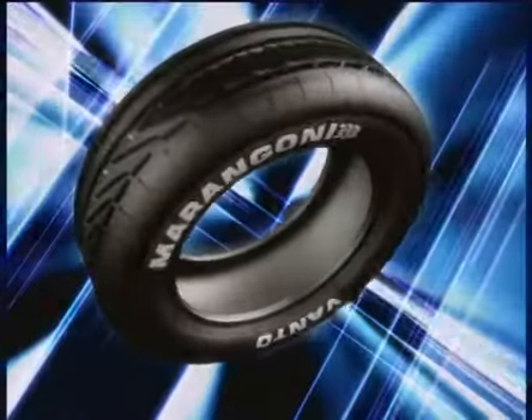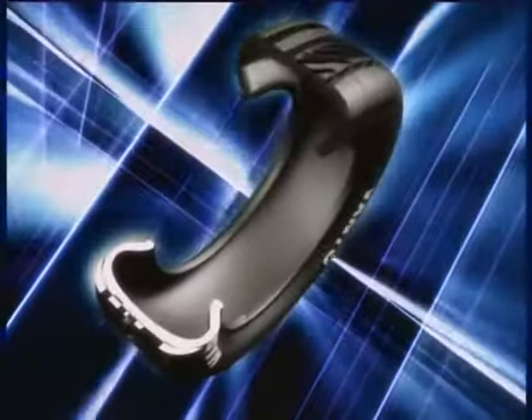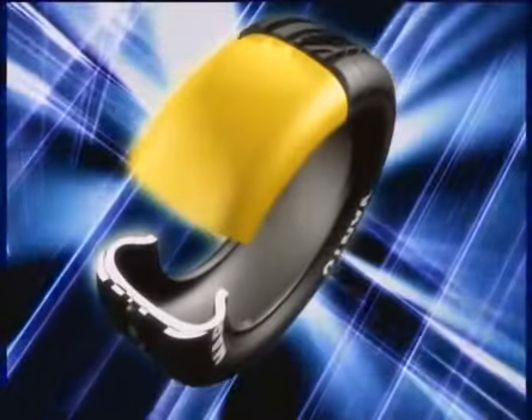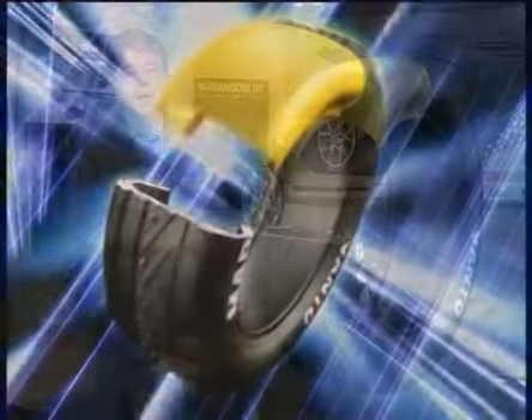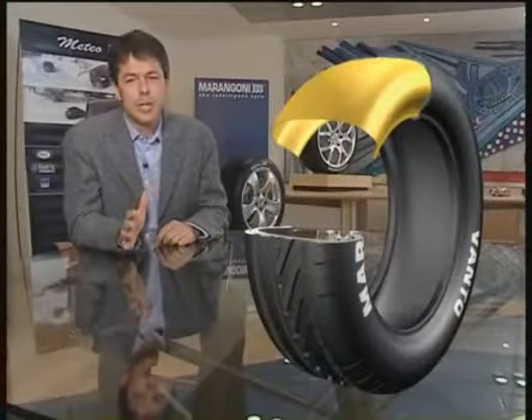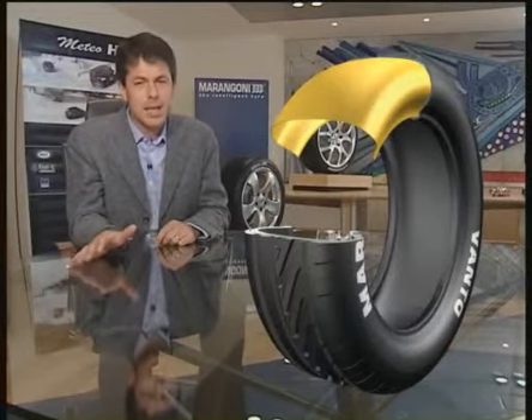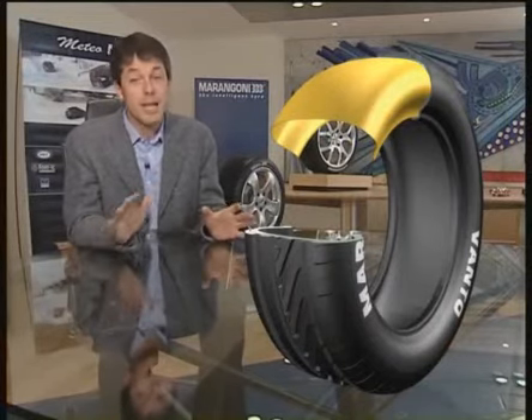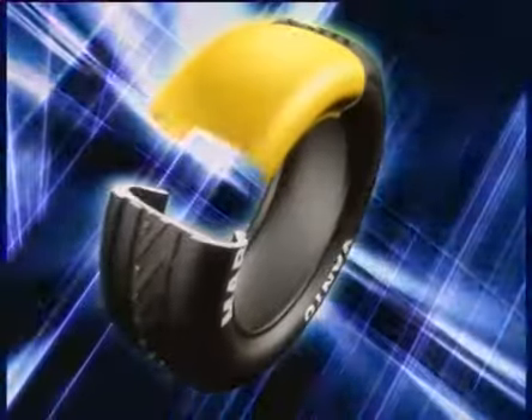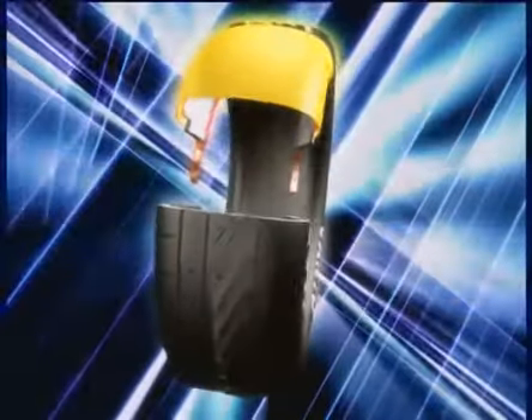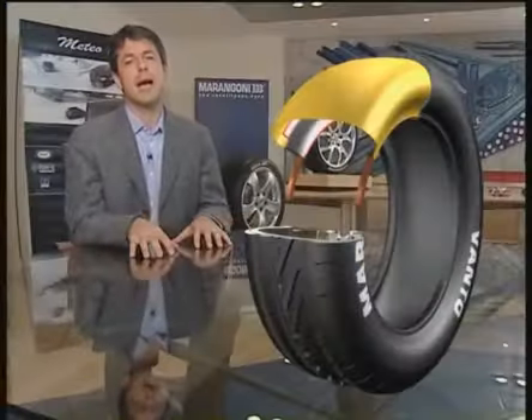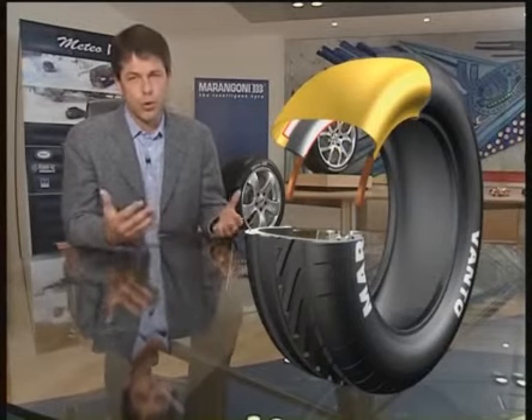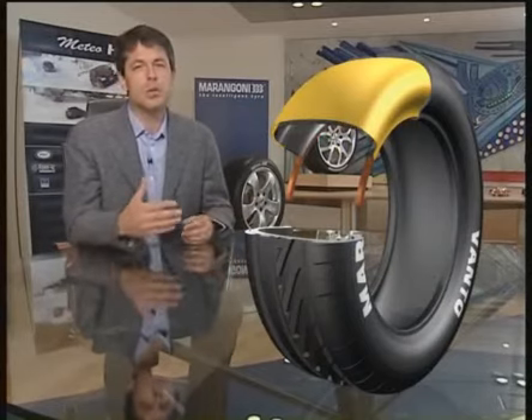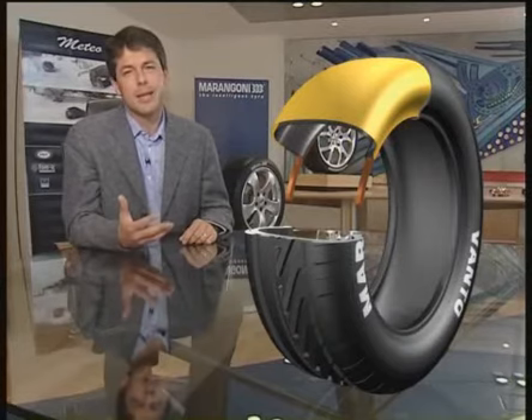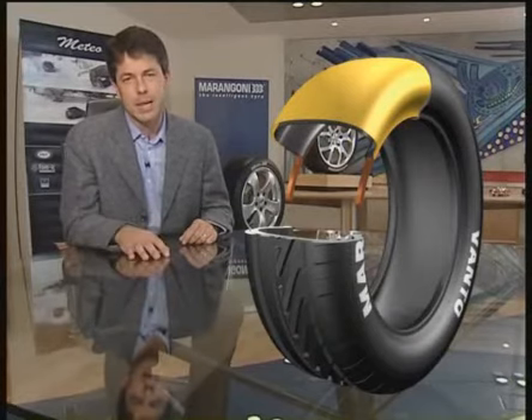The tire is made up of the following main elements: the casing, that is the load-bearing structure of the envelope containing compressed air. The casing consists of cords made of textile fibers set out in a radial arrangement around the bead wires. The bead wires are made of steel. Then comes the liner, that is the innermost rubber lining, made of a compound with special airtight characteristics.